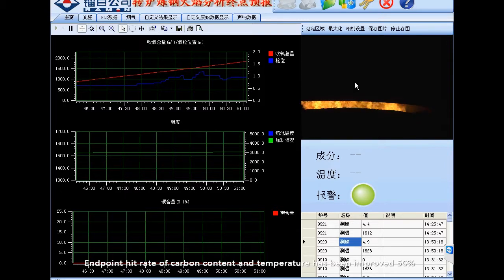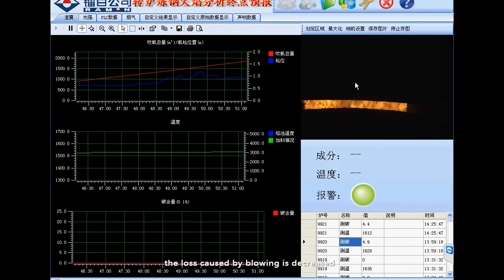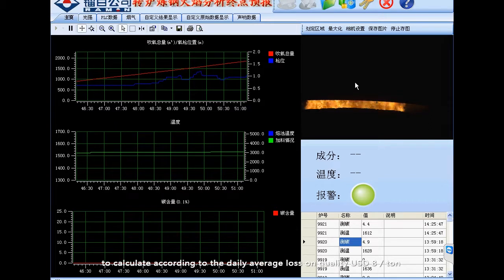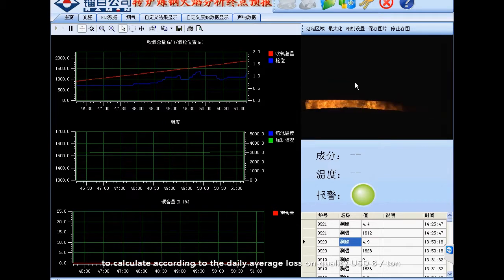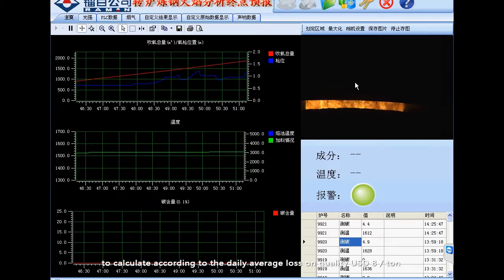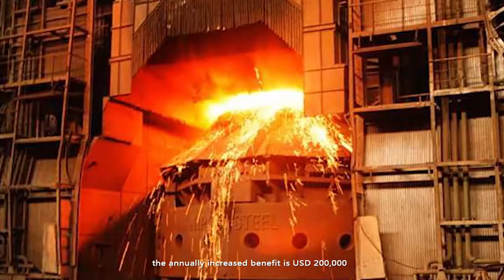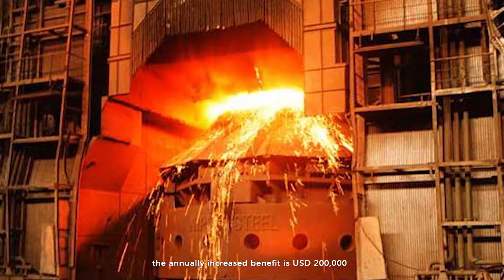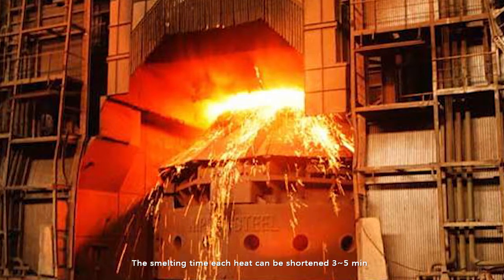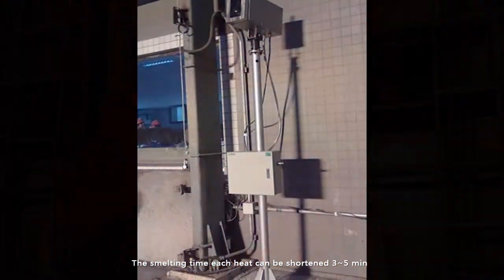Benefit analysis: endpoint hit rate of carbon content and temperature has been improved 50%. The loss caused by blowing is decreased. To calculate, according to the daily average loss on quality, $8 per ton, the annual increase benefit is $200,000. The smelting time each heat can be shortened 3 to 5 minutes.